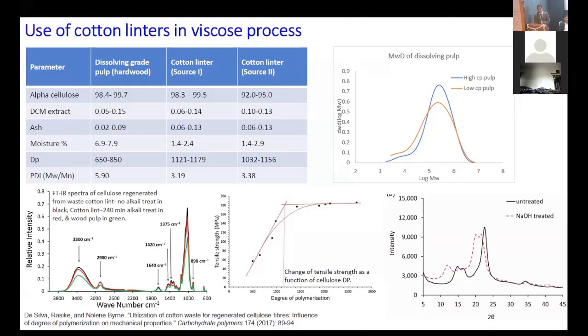The only part is that we are working on removing the dust from the cotton. That is the one thing, because that is affecting the filterability. And the other thing is how we can reduce the crystallinity and reduce the degree of polymerization. We are currently working on it, and we are getting some good results with a 10% blend. And we are trying to increase it so that we can at least reach up to 20% level to have some commercial trials.